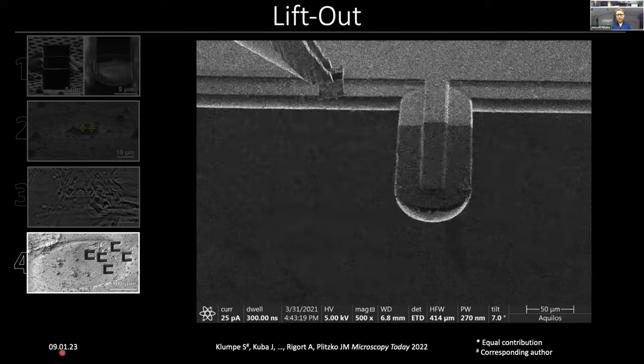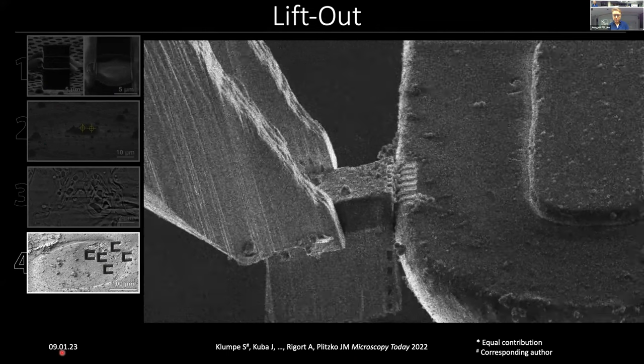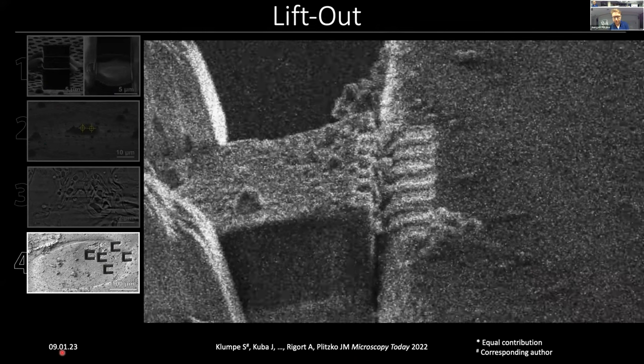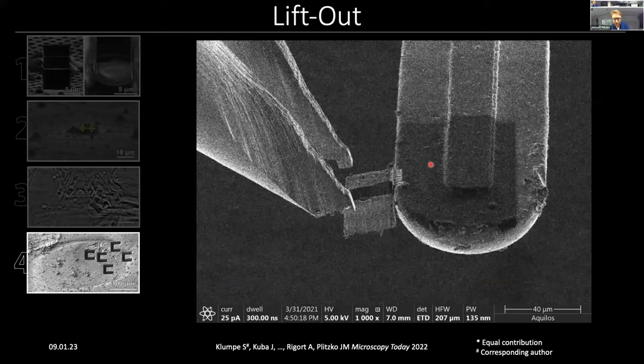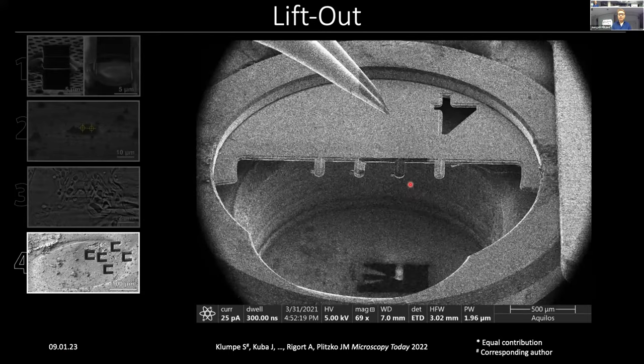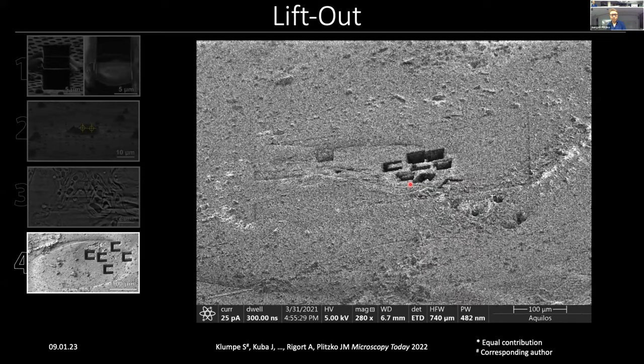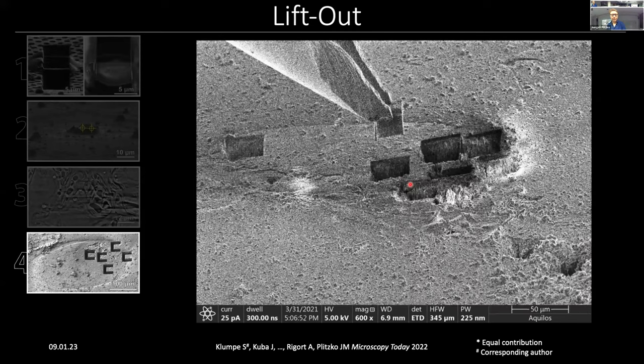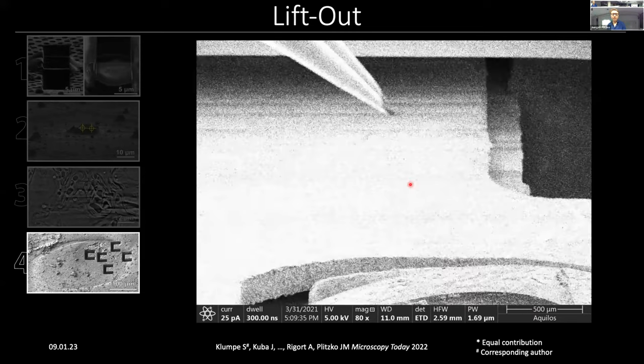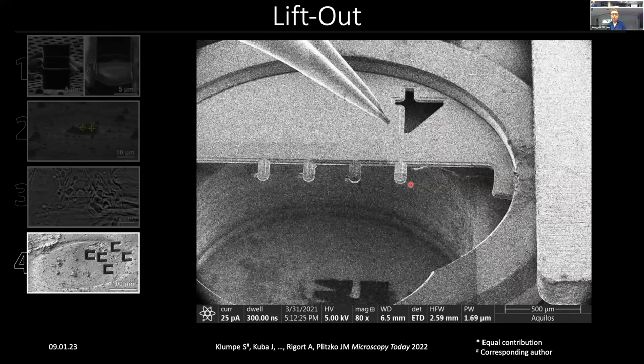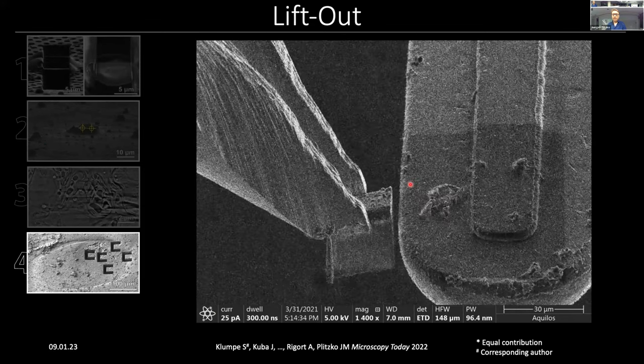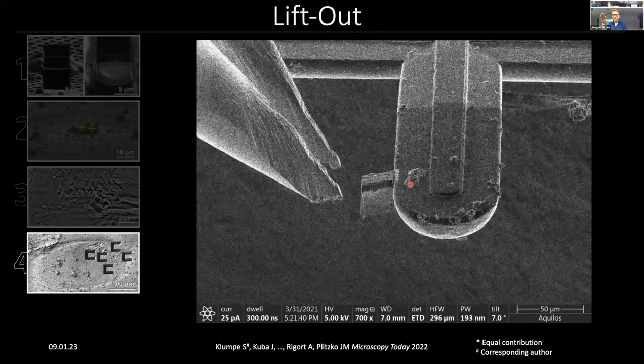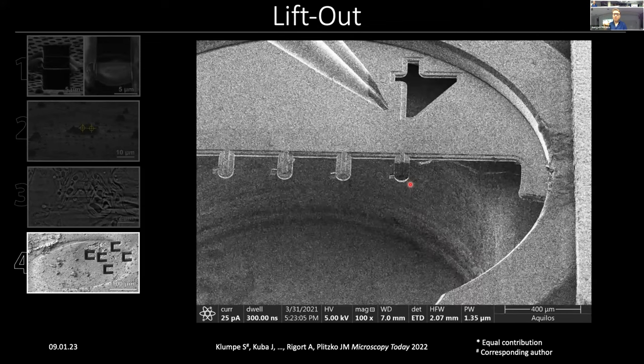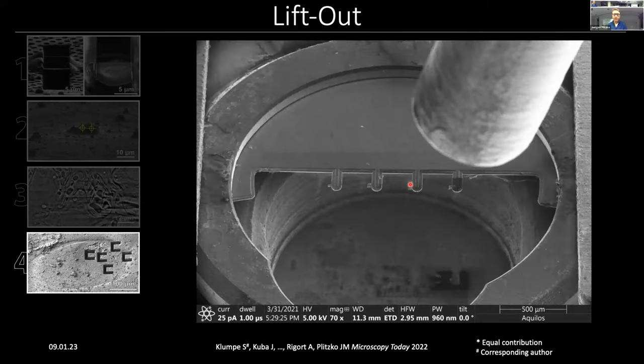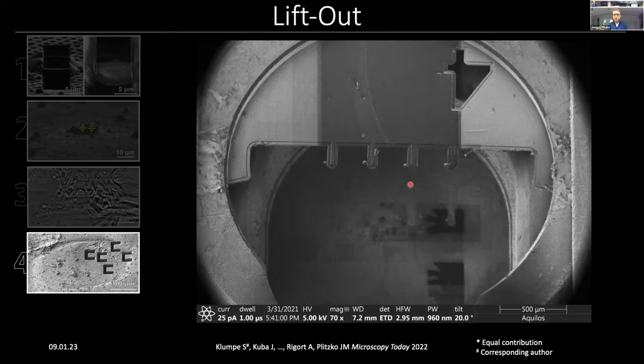And what we did here is then to use redeposition, as you can see these little microwell patterns here on the right side of the structure, to attach these little chunks to the side of the half moon grid. And then we can zoom in onto these extracted materials to take slices off with a focused ion beam and then take an SEM image of the exposed area. And this way you can really endpoint your structures inside the volume.